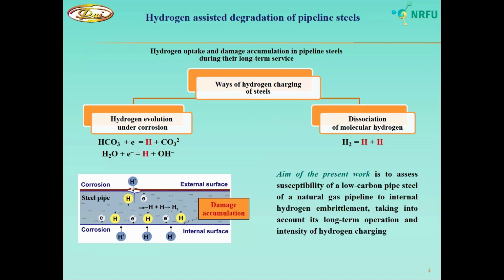On this slide, we can see how hydrogen is involved in damage and degradation of pipeline steels under operation. A pipe can be hydrogenated from inside and outside the pipe due to electrochemical corrosion. And what's more, under hydrogen transportation, it can also be evolved due to molecular hydrogen dissociation, especially on the fresh surfaces formed under deformation, for example, under cyclic loading. So a long-term mutual action of corrosion, hydrogen charging, and the mechanical working stresses facilitates development of damage at the nano and micro scales, and accelerates degradation.